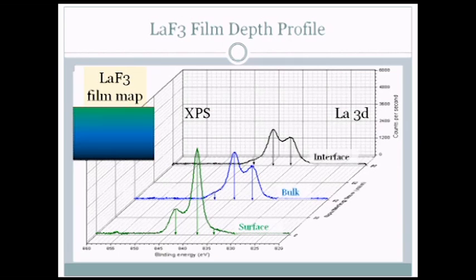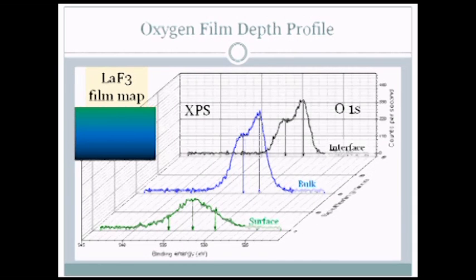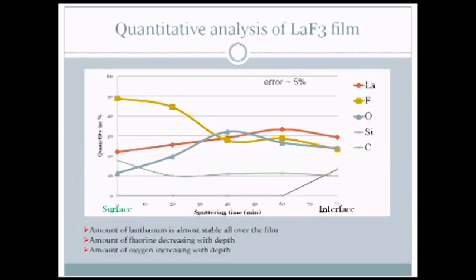Here are presented X-ray photoelectron spectra on the surface, the green one, which is in good correspondence with lanthanum fluoride. In the middle and at the interface, you can see an increase of the right shoulder, which points to the oxidation of the film. Oxygen spectra also prove this hypothesis. You can see quite a big increase of oxygen all over the film.